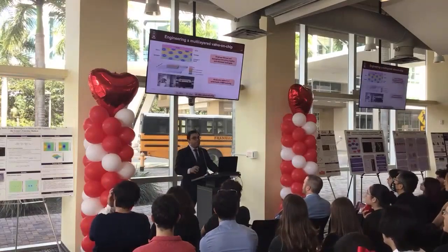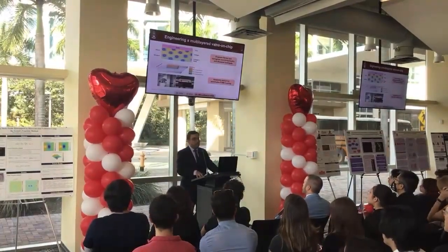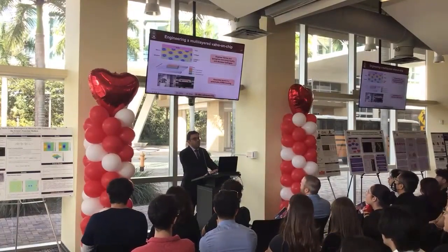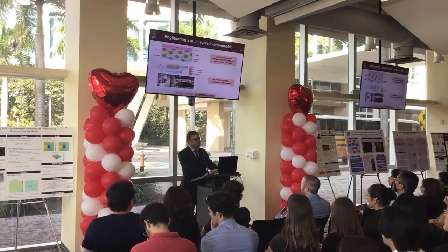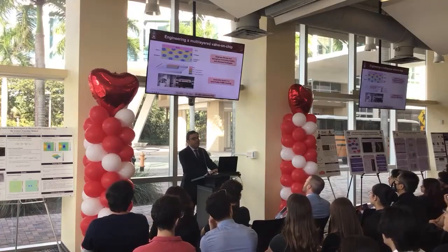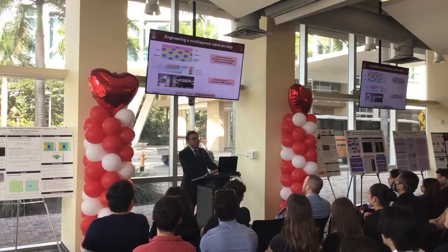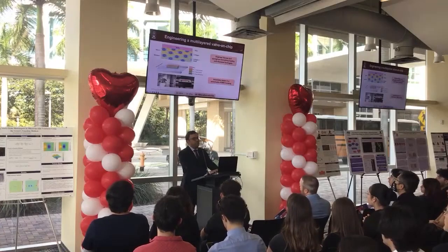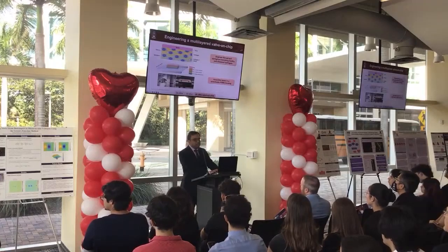Now we wanted to be able to then take this hydrogel and put it in a structure that will allow for imposition of mechanical forces. And to do that, what we did was to use a stretchable PDMS, or polydimethylsiloxane, silicone polymer housing. And so what we have here is 2 clamps holding a PDMS sheet, and within this PDMS sheet we had our housing that the hydrogel would be placed in, right, and bonded to, to allow for effective strain transfer from this moving sheet to the hydrogel itself.